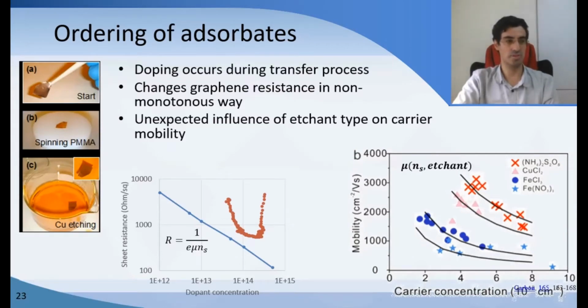And so normally doping is not a bad thing. Doping is a mainstay of semiconductor processing because you can change the resistance of silicon, let's say, by introducing controlled amounts of dopants. But if we do that with graphene, we find that there is no control. We see that first the resistance goes down, and then it stays kind of constant, and then the resistance goes up with doping again. So it's not following normal bulk semiconductors.